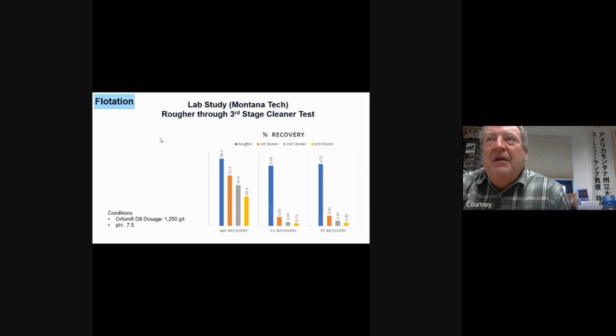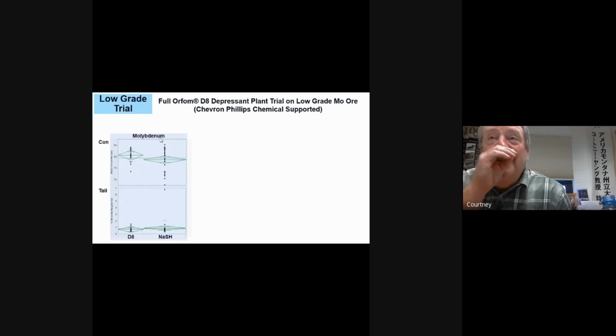Okay, and I'm going to skip that. I'm going to go on to the plant trials now. I cannot tell you where these were done. Chevron Phillips will not allow me to say that. But I can show you that when you are using D8, now this is an industrial setting, that your average grade is around 80.5%, somewhere in there. And you compare that to NaSH, and it's probably 79%. And so the D8 is performing much better than the NaSH. Okay, now this is the moly recovery.